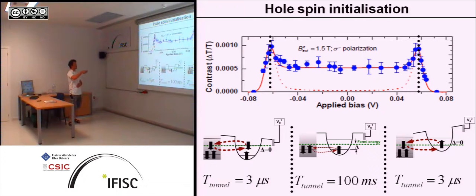The next graph shows the dependency on the gate bias, so this tunneling mechanism between the back contact and the quantum dot. So we see here we had resonance between quantum dot and the back contact. And because we just create this X1 plus state, and here we lose it again, that means here we have strong spin randomization at this point and this point, and that again means that we get the overall absorption signal back. In the middle now we have this plain line, but it doesn't show any bias dependency, and that's because we have 1.5 Tesla and the electron spin precession is already slow, and thereby we still get a significant amount of absorption. But the dotted line here is a fit of this result with theory describing this tunneling mechanism, and we use this to extract the tunneling speed between the back contact and the quantum dots. And at the two edges here we get 3 microseconds, but in the middle here we get 100 milliseconds. So that means that this process is irrelevant at the middle of this voltage plateau.